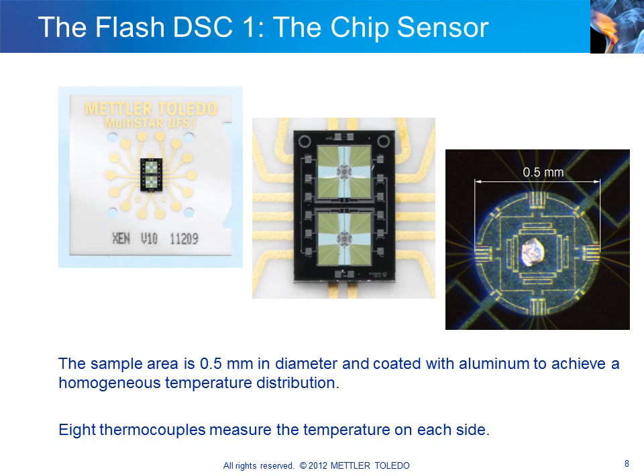The picture on the left shows the UFS-1 sensor. The membrane with the actual sensor is mounted in a ceramic frame together with the electrical connections. The picture in the middle is an expanded view of the actual sensor. It consists of two membranes with identical furnaces. Each sensor is in fact a complete DSC cell. In the picture, the sample is placed on the upper part of the sensor. The lower part is the reference, which usually remains empty. The high degree of symmetry of the differential sensor results in flat and extremely reproducible baselines. Even at the highest scanning rates, the measurement curves exhibit a degree of reproducibility never before achieved in a DSC instrument.